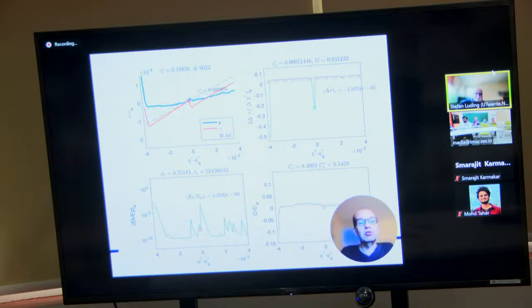And the plateau, this is the elastic area, and the event where the particles are moving around and rearranging, this is what I referred to as plastic, as irreversible before. So you can go from here before the event to another point before the event and back, that's reversible. When you go from before the event to after the event, you cannot go back. This is irreversible. Okay, and finally we look at the coordination number sometimes.